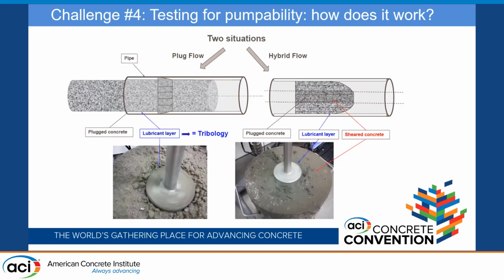You had a smaller section in the center that was your plug, and you had some sheared concrete off to the sides because of the low yield stress. That's what helped. We monitored that type of performance by changing the slag, changing the aggregate supply, and really focusing in on the admixtures to make sure that we had the right material to push this mix.